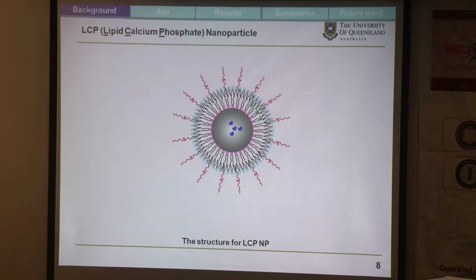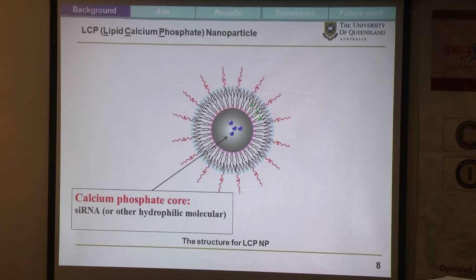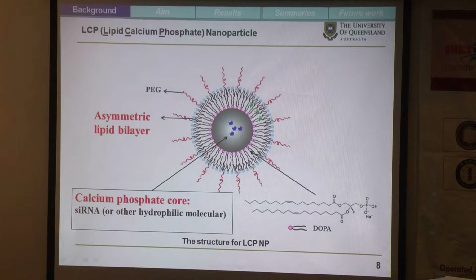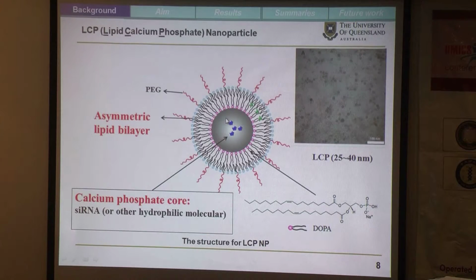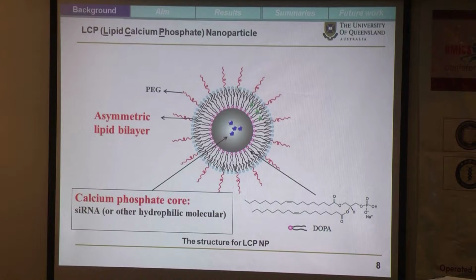Here I will address the structure of the LCP nanoparticles again. It contains a calcium phosphate core which incorporates siRNA or other hydrophilic molecules, and the outside is the asymmetric lipid layer with or without pegylation. The reason why the lipid layer can be coated outside the core is because the amphiphilic and anionic lipid DOPA, which has a phosphate group, can stay at the interface of the microemulsion and interact with the calcium phosphate core through binding with the surface calcium ion.